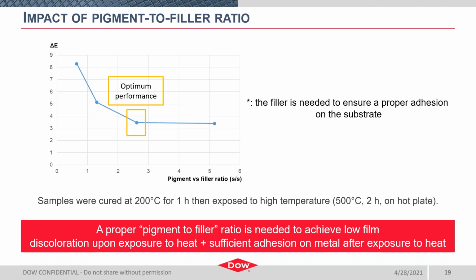As delta E increases, reminder, the color change is going to be more pronounced, so a lower delta E is, of course, preferred. From the chart, if you consider the obvious change in delta E and follow that trend line from right to left, silica loading increases, and this correlates to more discoloration of the coating after heat exposure. And the discoloration doesn't really stop changing until we hit a pigment to silica ratio of about 2.5, at which point that delta E is going to remain low, which is desired.